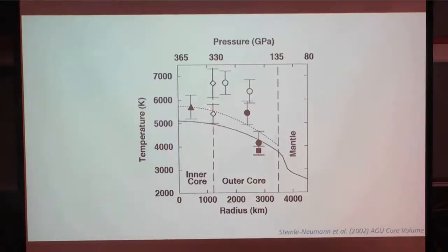And we know something about the adiabatic gradient in the outer core, so you can extrapolate upward to the core mantle boundary, and you end up with something like 4,000 degrees. And that's what that's based on.